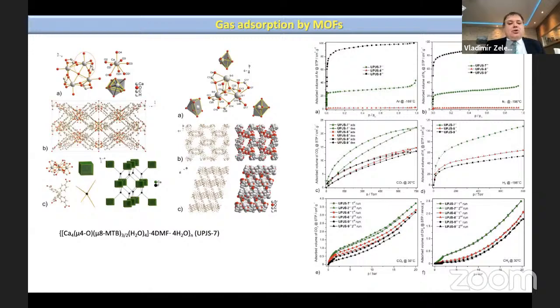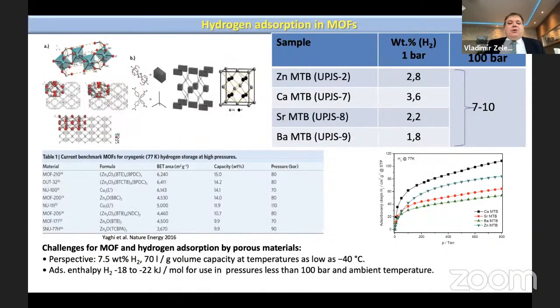And we also use these materials for hydrogen adsorption. Here on the graph you can see hydrogen adsorption on the calcium version of one of our compounds. Adsorption capacities at 1 bar are between 2 and 3.6 weight percent of hydrogen per 1 gram of adsorbent.